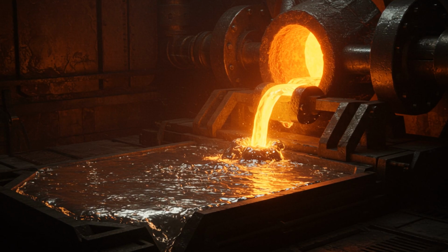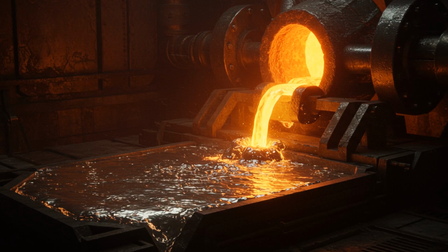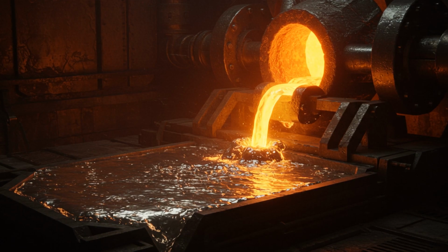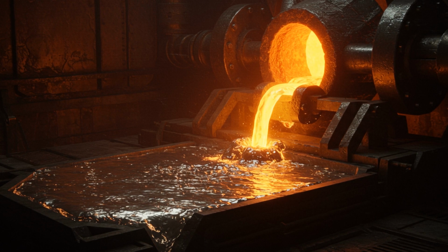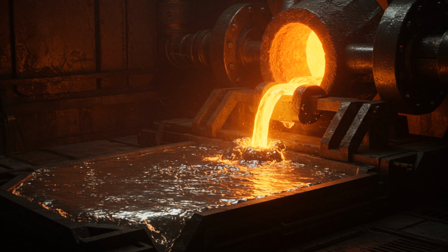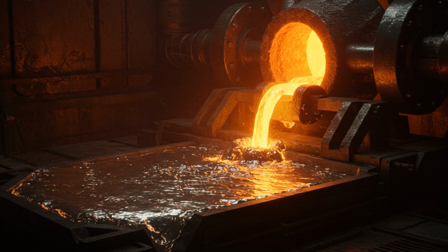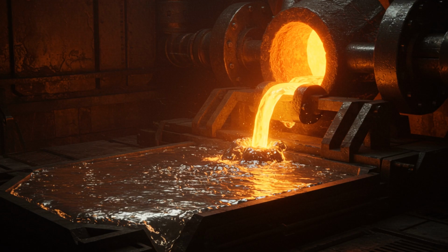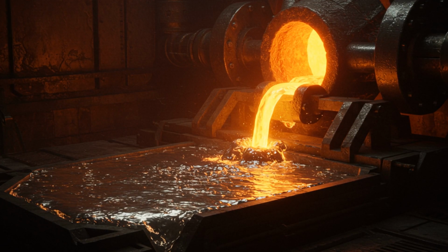There are no rollers, no molds, and no mechanical contact on the bottom surface, only the frictionless support of liquid metal. This environment is extremely hostile. To prevent the tin from oxidizing and ruining the glass, the chamber is filled with a protective atmosphere of nitrogen and hydrogen. The glass spans the width of the bath, forming a continuous ribbon. This is where the equilibrium thickness comes into play. Left to its own devices, glass on tin naturally wants to be about 6 millimeters thick. To make it thinner or thicker, engineers must use mechanized top rollers to stretch or compress the ribbon.